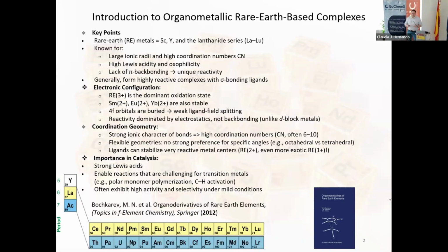Generally rare earth element catalysts are much more reactive with respect to different substrates as compared to the other transition metals. And this is sort of dictated or governed by high electropositivity of the metal center and high oxophilicity. Oxophilicity also makes a problem because this shows the tendency of metals to establish quite stable metal-oxygen bonds, which reflects, let's say, poor thermodynamic stability in the presence of oxygenates, so molecules containing oxygen.